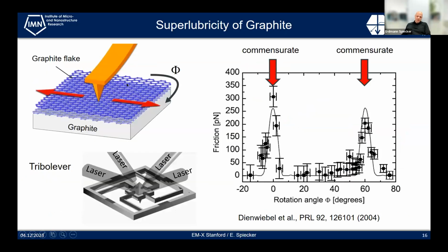And I want to show this briefly. So he moved a graphite flake on top of graphite, and then he assumed that the graphite flake was attached to the tip, and he could then rotate the graphite below and measured the sliding friction force with a special tribo lever as a function of twist angle. And you see here the lock-in at 0 degree and 60 degree, where you have strong friction forces, and in between you have very low friction due to the incommensurate or quasi-incommensurate structure.